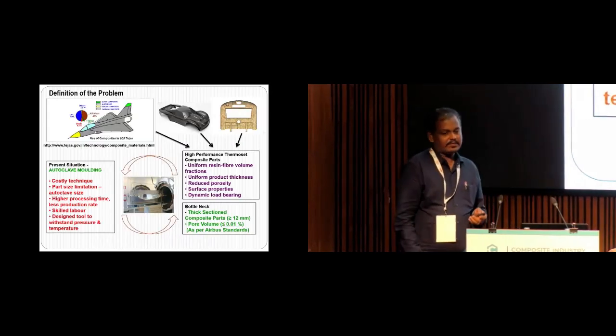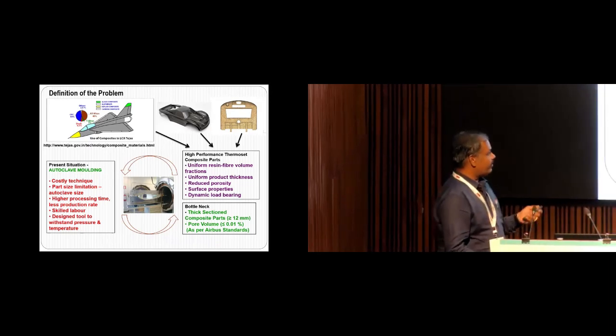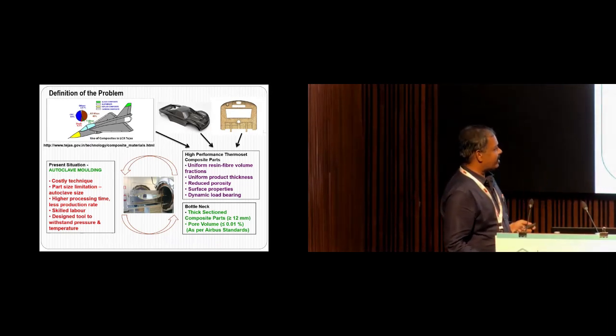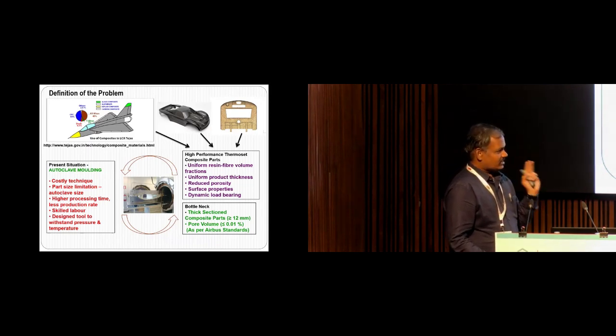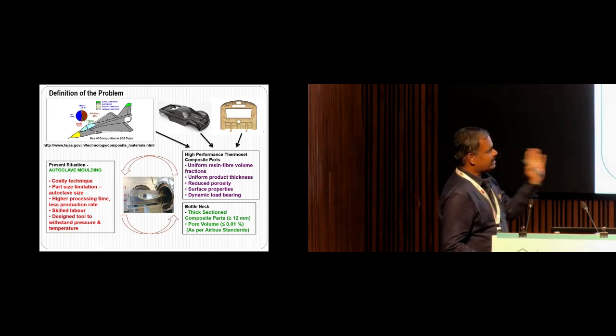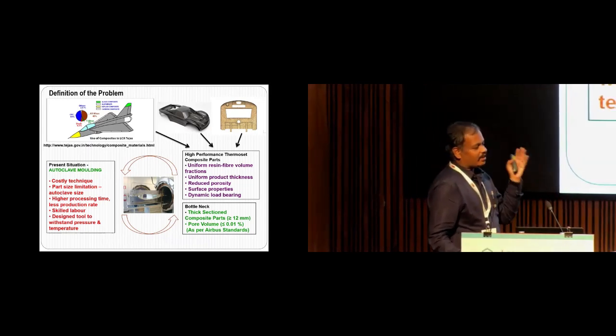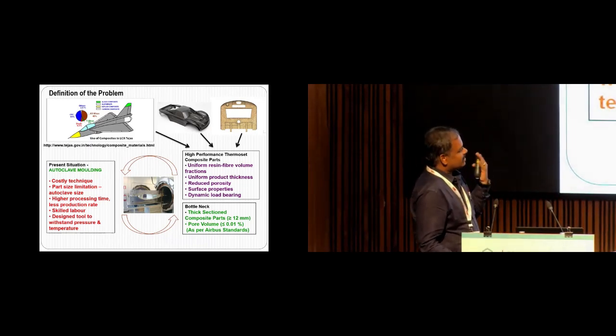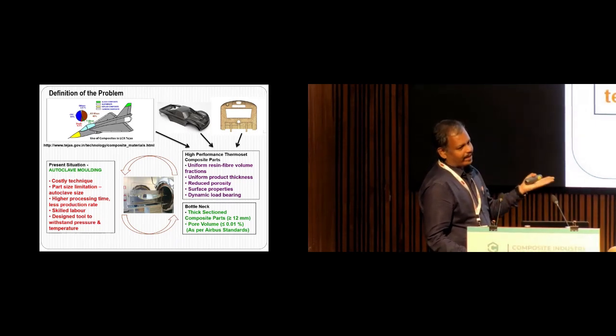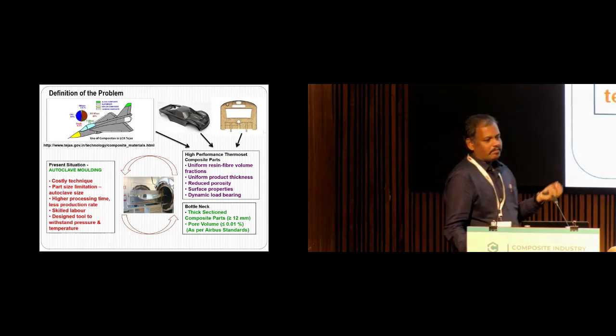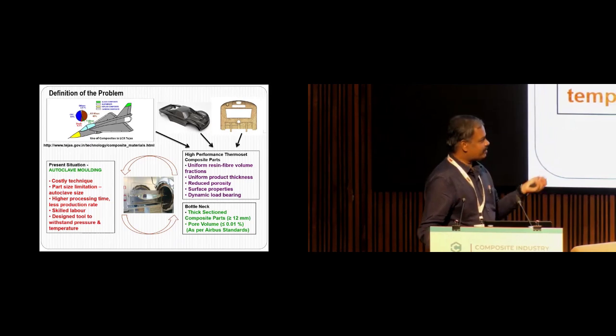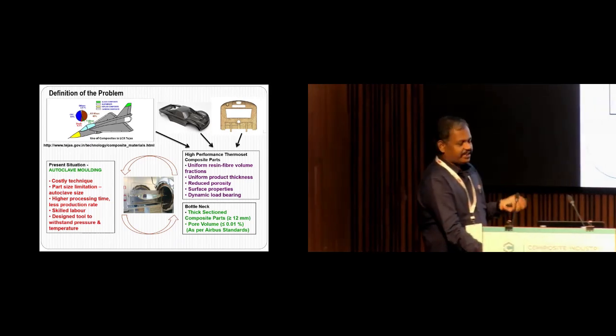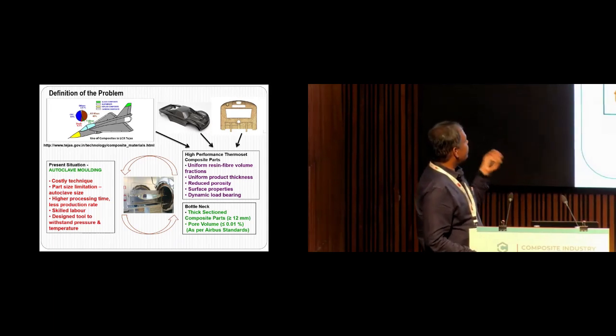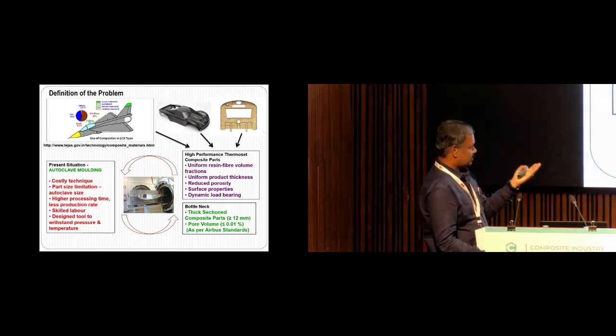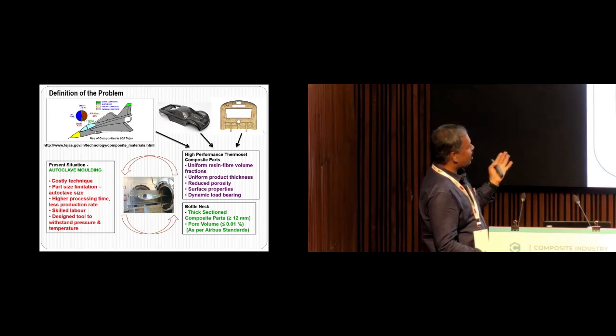So here comes the definition of the problem. When you come to aerospace composite laminates, two restrictions, two bottlenecks are there. One is we cannot manufacture a composite laminate having a thickness of more than 12 mm. Next one is you have to have a pore volume less than 0.01% as per the Airbus standards. And generally in Airbus, we manufacture thermoset composite parts using autoclave molding.